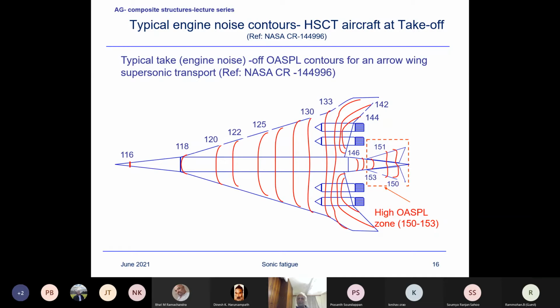And so for the testing to determine reliability, normally it's difficult to test a coupon and just mechanically keep on loading at lower frequency. So usually for testing sonic fatigue coupons, in order to generate the high cycle fatigue, shakers are used, which can run at high cycles, so that the test doesn't take much time.